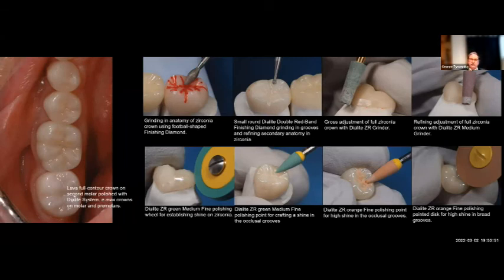So let's take a look at a couple of cases here. One is a zirconia and lithium disilicates. Again, on the zirconia, we use water spray, very, very fine diamonds. We adjust the restorations as necessary. We adjust the anatomy. Then there are a number of different polishers available to us. Dialite is one of the leading brands in providing high shine for glass ceramic materials. We can adjust it with the grinder, refine it with the medium grinder, and then go through the sequence from medium fine, the green materials, to the orange, which is the fine material, and then providing a very nice fine polished surface that can be functional and dynamic in the functional areas of the oral environment.